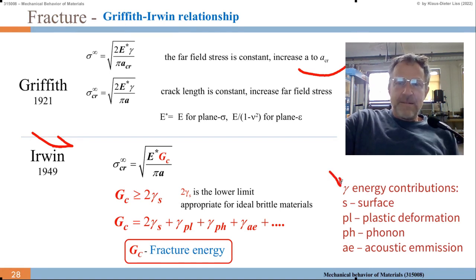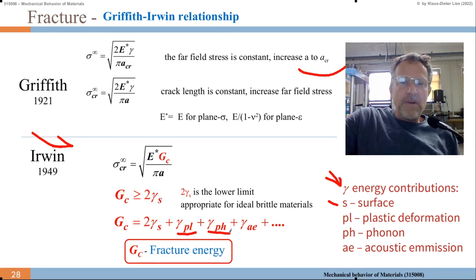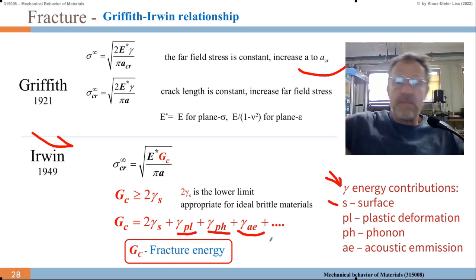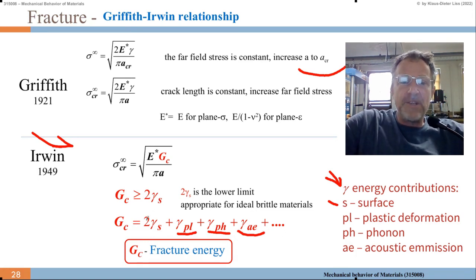But there can be other contributions. We have the surface contribution, but there can also be a plastic deformation contribution. You can emit phonons, lattice vibrations into the material, or acoustic emission, a whole spectrum of phonons, and other things. All these processes cost energy, and therefore Irwin replaces this gamma or 2 gamma by what he calls the fracture energy GC.